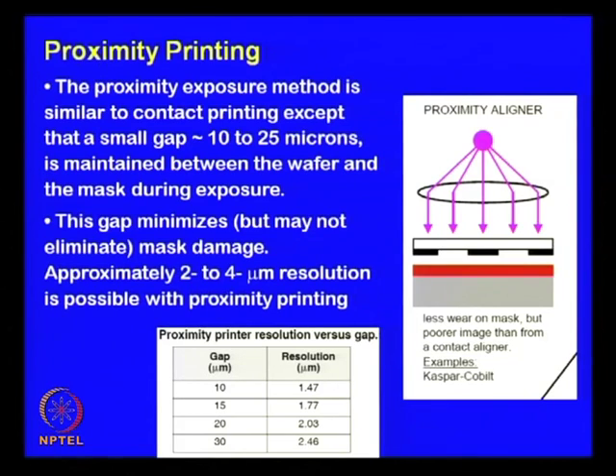And the resolution, however, this comes at a cost. The resolution is not as tight as you typically get in case of a contact printing. But please realize that in industrial stage at the present moment, the present technology uses neither contact printing nor proximity printing. So, this table gives you an idea about what sort of resolution you might get as a function of the gap between the mask and the film. So, here you can see that this is the mask, this is the film. Unlike a contact aligner where the things were in direct contact, here the two are not in direct contact.